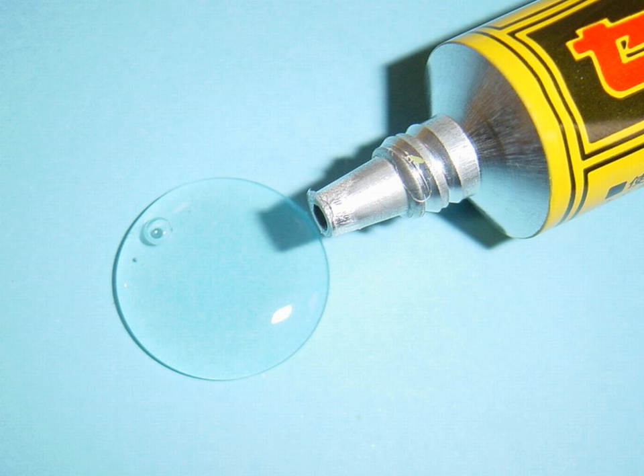To solve this problem, surface treatment can be used to increase the surface energy as a preparation step before adhesive bonding. Importantly, surface preparation provides a reproducible surface allowing consistent bonding results. The commonly used surface activation techniques include plasma activation, flame treatment and wet chemistry priming.